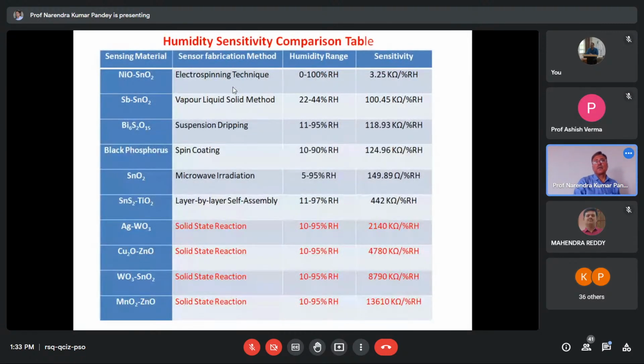You see, from various sources, I have taken the sensitivity reported in literature. For example, NiO, SnO2 electro, they have a sensor fabricated through the electrospinning technique. Humidity range was 0 to 100 and sensitivity was 3.25 kilo ohm per percentage. Here, by this method, this material, 100 kilo ohm per percentage. Here, by this method, 118, 124 kilo ohm. And all the materials that we are doing, Ag doped WO3 by solid state reaction route, this is the range of relative humidity, and we are getting 2140 kilo ohm per percent. You compare these ones, how high a sensitivity we are getting.